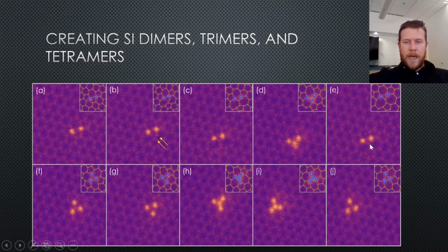And then it is actually recaptured, and these 2 carbon atoms that participated in the bond rotation are knocked out and replaced by a silicon. So now we have a silicon trimer, which is like a rotor that can be flipped around in the lattice. And this was fairly freely able to rotate with the beam. If you zoomed out, or if I zoomed out, I was able to agitate